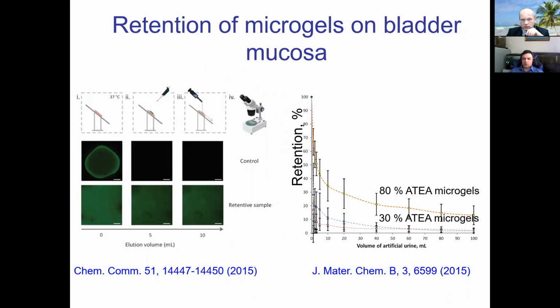If it is the ocular delivery we're interested, then we wash it with artificial tear fluid. If it is the urinary bladder, for example, then we wash it with artificial urine. And then each wash we analyze by taking fluorescent images and using image analysis. And the graph on the right shows that the microgels with 80% of thiolated monomer gave us massively higher adhesion, massively higher retention compared to the particles that have lower levels of thiols or the particles that don't have thiols. So that was one of the systems we developed.